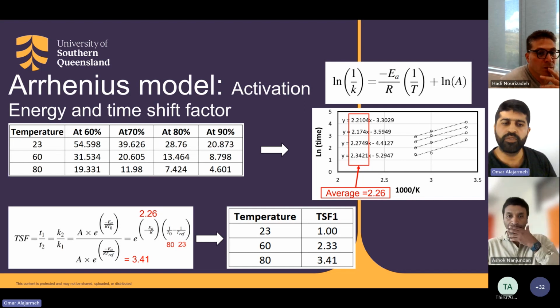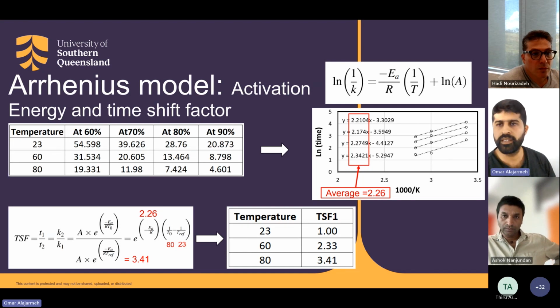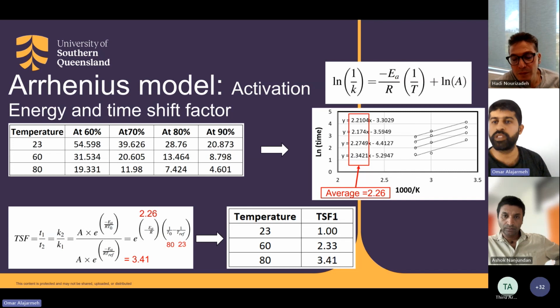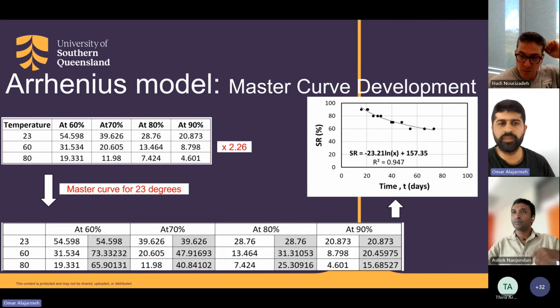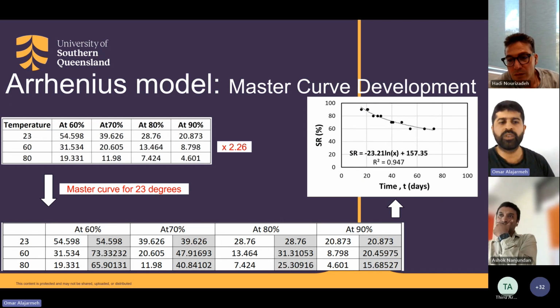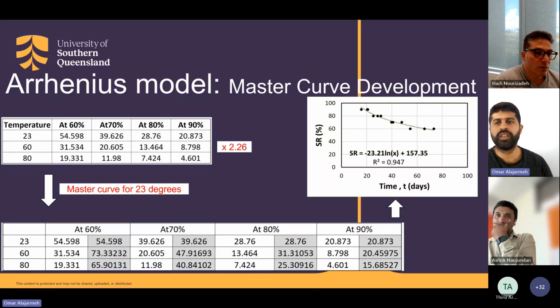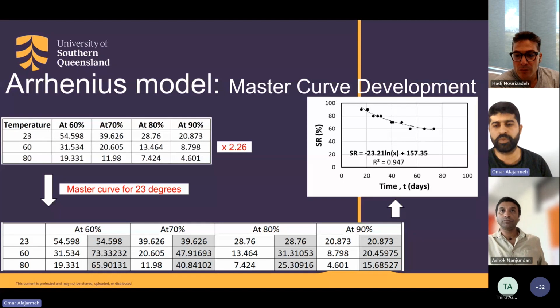For example here, if you are changing from room temperature to 80, the time shift factor is 3.41. That means if you age your material at 80 degrees, it will reduce by 3.41 the duration compared to testing at 23 degrees, or room temperature. Once we have that time shift factor, we go again to the table that we previously constructed, and multiply all the other temperatures by their relative time shift factor. This process is called developing a master curve. A master curve has a lot of representative dot points to give a reliable relationship that indicates the service life of the polymer.